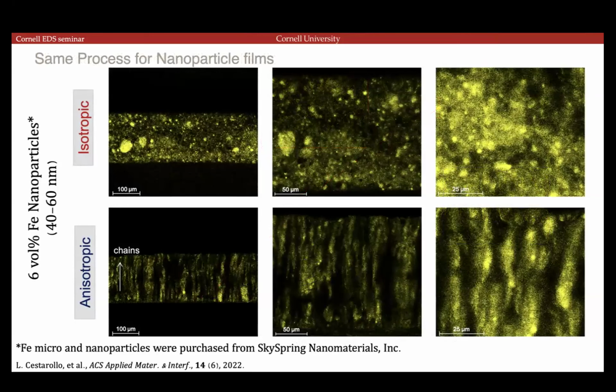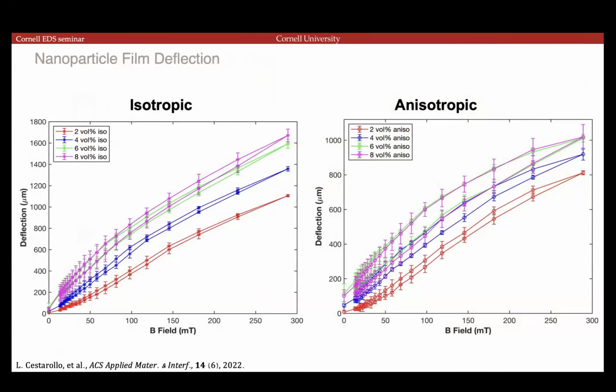So we did the same comparison with nanoparticles. These are 40 to 60 nanometers in diameter, and we made isotropic versus anisotropic films with both, and then compared them as a function of volume percent, and also looked at how much deflection happens at the small field range. The interesting thing that we'll see here, if you remember what I said about the main difference between microparticles and nanoparticles, is how much deflection can you actually produce in a low magnetic field?